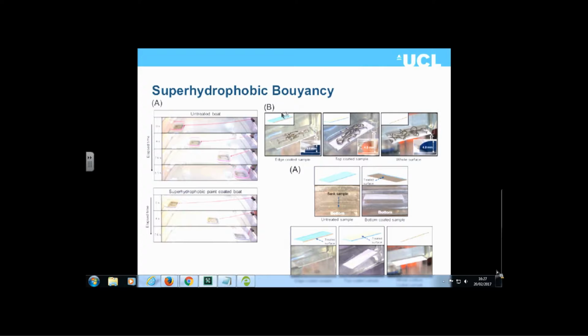We've also looked at taking a glass slide and loading it with various metal pins or weighting. The glass slide on its own, with no superhydrophobic coating, will sink. We looked at what happens if we coat just the edge, the top, or the whole surface, and the degree of loading we can achieve. We can get a depression of the water by about 4 to 5 millimeters once loaded with these materials. Part of that is because the superhydrophobic coating traps a layer of air at its surface, but also due to water repellency from the coating.